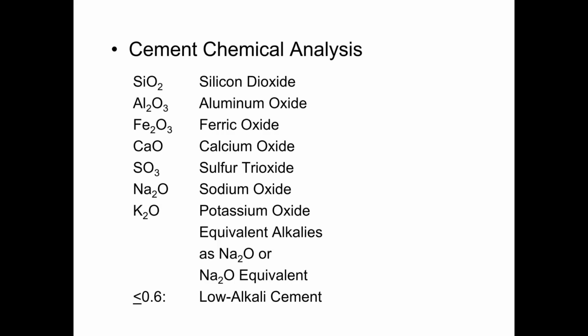So generally what I recommend to the plant that I'm reviewing their mill report is that they request that the cement supplier provide them with mill reports that indicate the alkali content because the cement supplier has the data, and so it's just a matter of putting the data on the mill report. And usually the cement supplier will be accommodating since they do already have the data. So it's the potassium and the sodium oxides that we're primarily concerned with. There are other limitations on the other oxides as well.